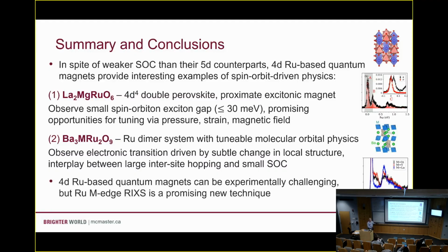And lastly, from an experimental point of view, these RIXS experiments in general are not easy. The M-edge experiments are even harder because the intensities are so much weaker. But if you have these 4D transition metal materials, there's really a lot of interesting information that you can pull out here, and a lot of parameters that are hard to get in other ways.